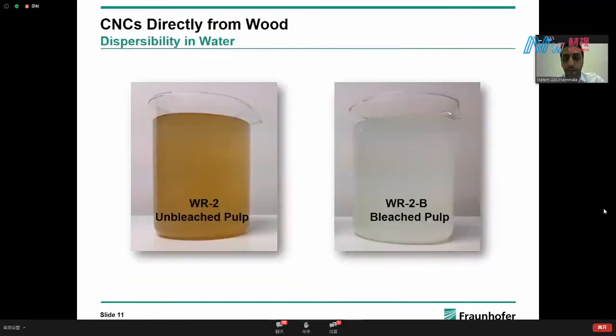And here we go. The pulps I produced from this process, unlike traditional pulps, are highly dispersible in water. The moment you put them in water with very mild sonication, you can get really nice suspensions, as you see. This is obviously not the case using pulp fibers. If you bring pulp fibers, any one of us, and try to disperse them in water, that's not going to be the case. They will immediately precipitate.